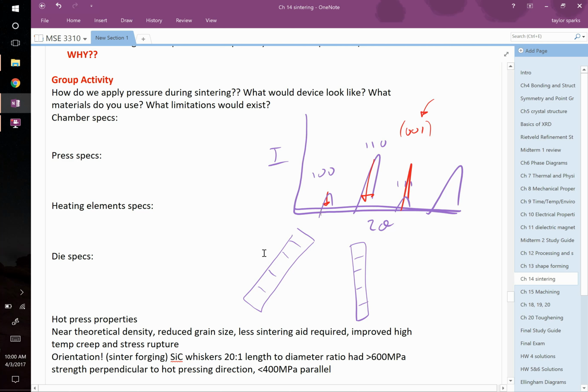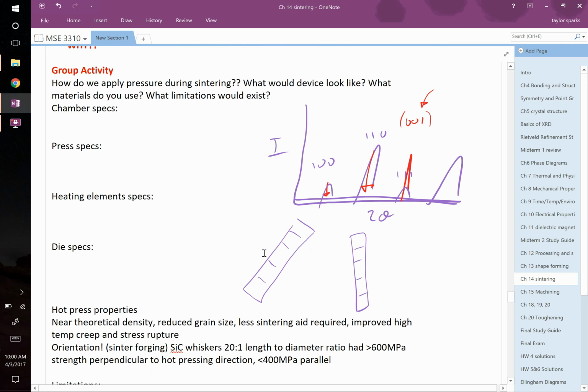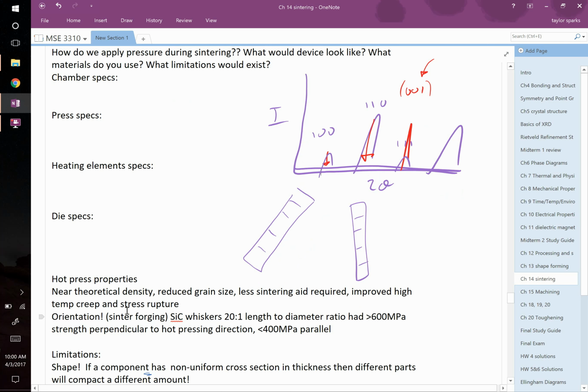Okay, so we've talked about the fact that this is going to orient your samples, and you see that really quite a bit, right? So, for example, here, they'll call this sinter forging, which is when you achieve this orientation as you're sintering it under a press, so under a forge, right? So silicon carbide whiskers that initially had like a 20-to-1 length to diameter ratio, so they were like these long little rods of silicon carbide. They had strength over 600 megapascals, perpendicular to the hot pressing direction, and only 400 megapascals parallel to that direction.